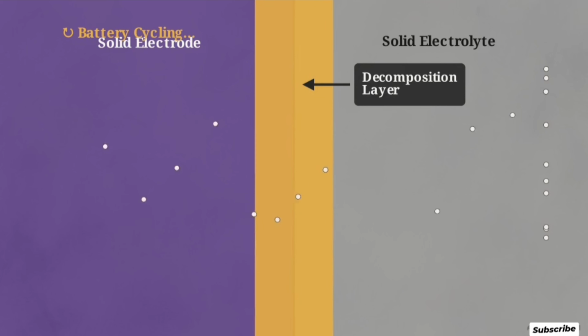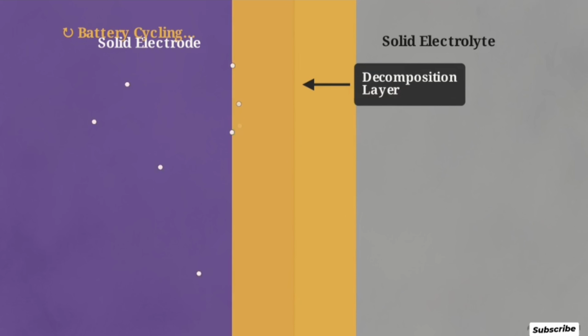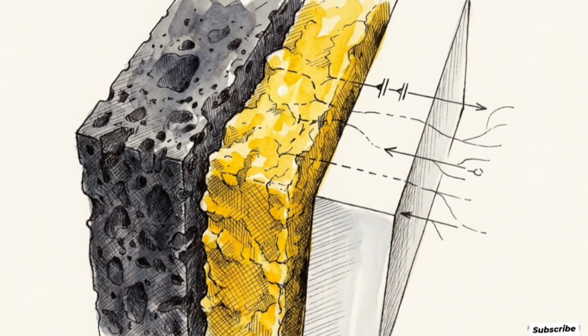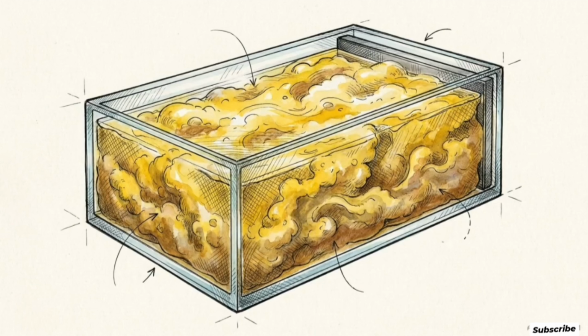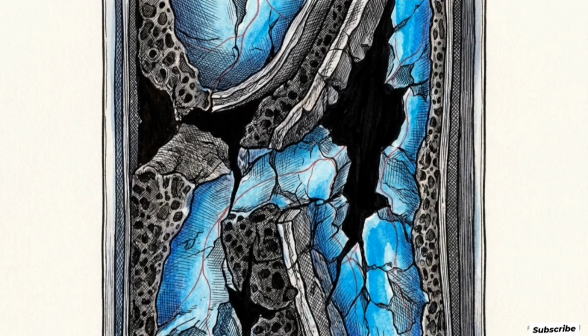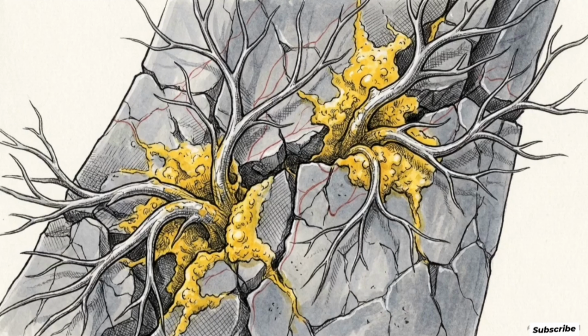Every time the battery cycles, this layer thickens, catching and trapping ions as they attempt to pass through. This growth chokes off ion transport, essentially starving the battery of its ability to move energy. Even without a physical break or a short circuit, this chemical rot eventually suffocates the cell from the inside out. We are left with a cell riddled with dead zones, shattered ceramic, metallic veins, and chemical sludge.